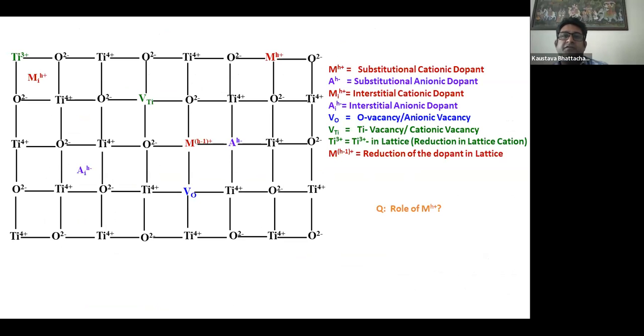So basically what we think of in doping is that if we dope in a structure, for example, if we dope an M+ ion in the titanium structure, it can either replace the titanium 4+ and dope there, or it can go to the interstitial. So it can be either substitutional doping or interstitial doping. Now it depends upon the charge of the dopant, as it has to maintain the overall lattice charge. In order to do that, it can create some anionic vacancy or a cationic vacancy depending upon the type of doping we're doing.